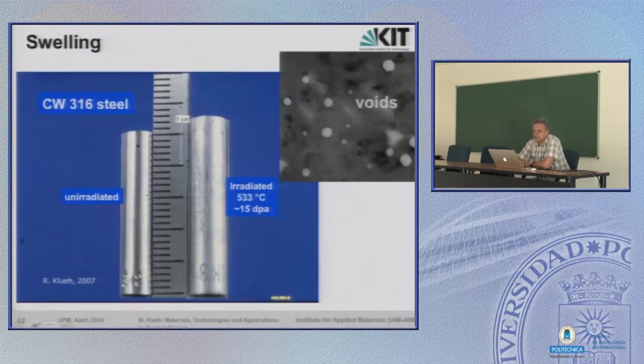This here is an austenitic stainless steel before irradiation, and the same piece after irradiation. And well, it goes without saying, this thing has increased its size. And this is called swelling, because swelling correctly describes what you see here. The material really and virtually swells under irradiation if it forms stable and many voids inside. So this, in one word, is the effect of voids during and after irradiation.